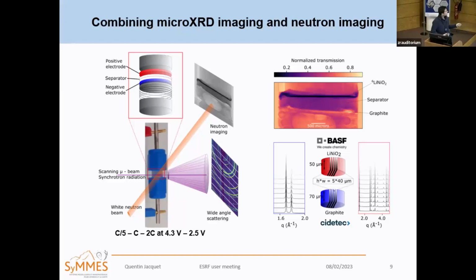For the other technique, neutron imaging, we're using a wide white neutron beam. We're illuminating the whole cell and getting radiographies where the contrast is proportional to the lithium concentration. In this image, for example, you're seeing the LNO electrode, which, when the battery is discharged, is the electrode containing the lithium. Just before that, we cycle the cell at different C rates to look at the impact of the charging and discharging speed on the heterogeneities in that voltage range.